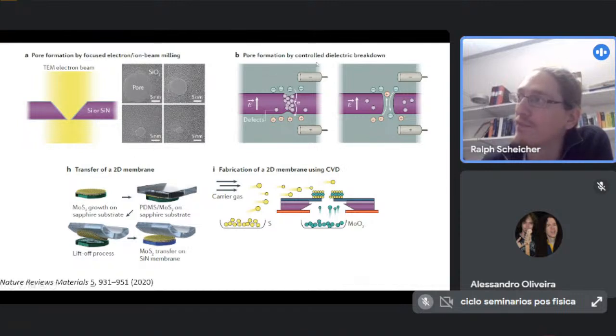Or you can use something called controlled dielectric breakdown. There you take a membrane and you apply a relatively high voltage across it, and any kind of real material contains certain defects. And typically a defect in a material often comes with a charge. So it has some kind of excess charge, plus or minus. The electric field will lead to some acceleration there, and it will try to move some of the ions that are in the vicinity of the defect. Typically, this process then creates more defects, and then you get even more acceleration of ions, and so on, until eventually the material breaks down and you really get a channel now where the material allows ions to go through, basically the nanopore that you want to create.